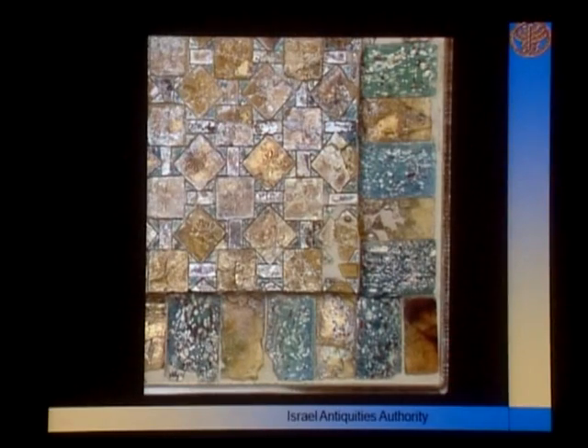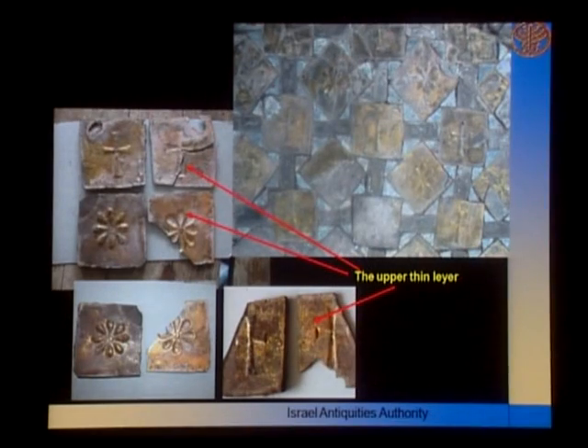The panel is made in the opus sectile technique, combining pieces of various shapes and sizes. On the frame are large plain gold glass tiles and mosaic glass tiles alternately. The gold glass pieces in the panel are small. The squares are about 5 by 5 centimeters, and the rectangular and triangular ones are even smaller. The square pieces are decorated with relief motifs, a cross and a rosette of 8 leaves. So far, we have not traced any parallels for this type of gold glass tiles or inlays, neither in excavations nor in collections.